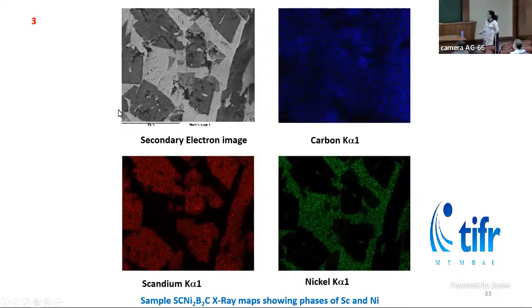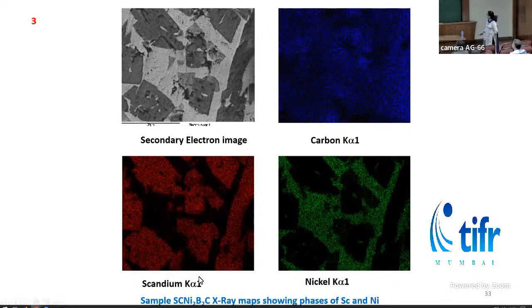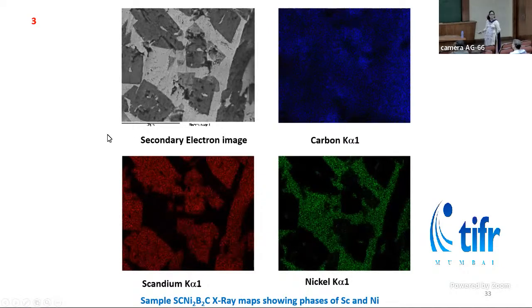We can also take an X-ray map of the sample and calculate the area of the different phases using the image. So this is an SEM image of a scandium nickel 2 boron 2 carbon sample, and this sample is also a multi-phase sample. Here also we can see that this gray phase is rich in scandium by looking at the scandium K alpha X-ray map, and this bright phase is rich in nickel. So the nickel K alpha map shows that this bright region is nickel rich.